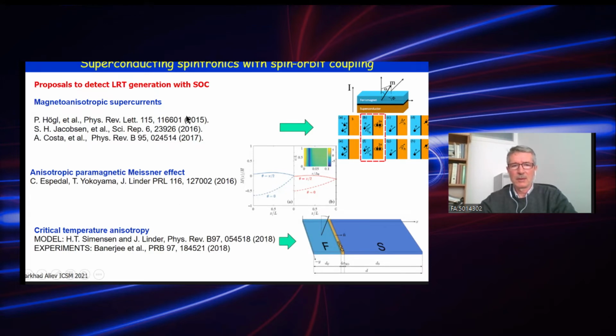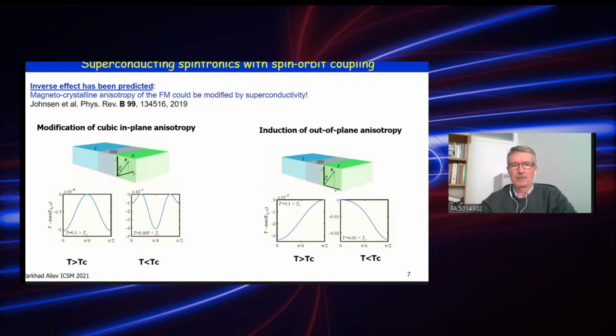Our main proof comes from the observation of magnetanisotropic zero-bias effects in this structure. As I mentioned, an inverse effect has also been predicted: a system presenting coupling between superconductor and ferromagnet via spin-orbit coupling, deep in the superconducting state, may suffer a change of in-plane anisotropy if the system is fully epitaxial, and also out-of-plane anisotropy.